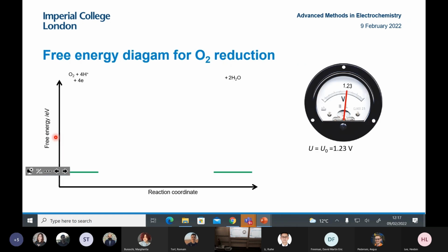So if you look at the free energy diagram for oxygen reduction, this is at the equilibrium potential. So at the equilibrium potential, you have the same free energy of the initial reactants and final products. Then if you apply an overpotential, the whole reaction is downhill in free energy. Because there's 4 electrons in the initial reactants relative to the final products, the actual change in free energy of the initial reactants relative to the final products is equal to 4 times the bias you apply.